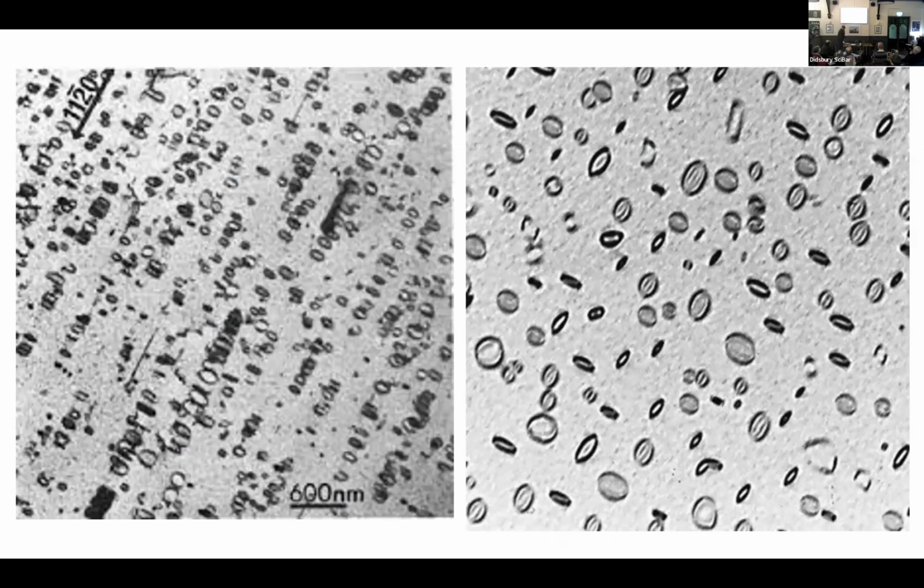Next thing they can do, because they can do a lot of things. Take my analogy back of a line. What happens when we take a line and we tie it back on itself, make a loop? These defects that we've now introduced as a result of radiation can clump together in different ways. So now if I take a handful of atoms and stick them in, it looks all right from the inside, but now it's bulging out of the sides because I've just rammed a few extra atoms in there where they shouldn't be.